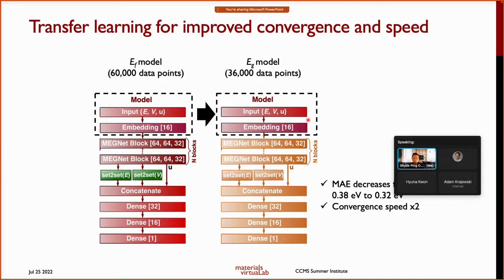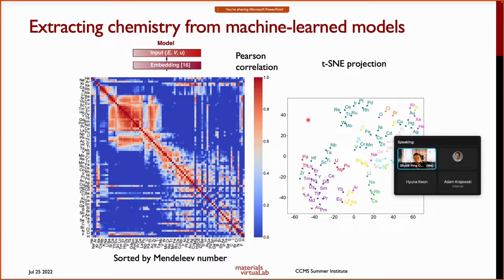Okay. Now, one of the most exciting things about graph-based deep learning is that because it's such a natural representation for materials, we found that when you actually train your MEGNet models on things like the formation energies, the model itself actually learns chemistry from the data, right? So here what we did was that we took the length 16 embedding vector for each of the elements, and we basically plot the Pearson correlation coefficient between pairs of different elements, right? So this plot basically shows you the pair correlation between the embedding vectors for each of the different elements with every other element, and we actually sorted the elements by Mendeleev number.